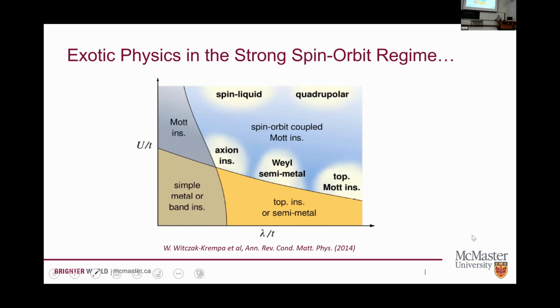So this is a cartoon phase diagram that sort of makes the philosophical point that we're looking for here. So what we've done is we've got a graph that's showing you electron correlation strength along the vertical side here, and then spin-orbit coupling along the horizontal. And so this bottom corner here is what we might think of as kind of, I don't want to be mean, but boring materials, simple metals, band insulators, things that are easy to understand. The 3D transition metals are sort of up in this range. If we crank up the electronic correlations, then we can get unusual insulating states, so-called Mott insulators. If we just crank up the spin-orbit coupling, we can get topological insulators or semi-metals. So these are both interesting regimes to work at.